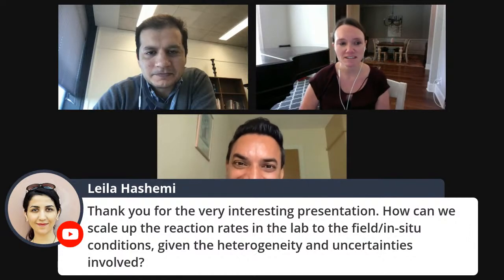Yeah, so that's something we're really working on with our accessible surface area investigation. Thinking about the way we're modeling reaction rates at the continuum scale or larger scale, we usually use that transition state theory rate law. That's great because we can easily include that in our large scale simulations. But really the largest source of uncertainty is what you put as that surface area value. Our work so far has shown us that accessible surface area is potentially a better approximation than some of the more simplified approaches that we've been using. What we hope is that this can improve simulations at the larger scales using an accessible surface area value, at least compared to the variations we get using geometric surface area or specific surface area. And that looks promising so far.